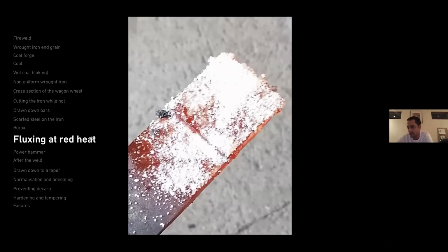It cools down quickly and you have to work fast, but not unnecessarily hastily. It has to come right almost on the first time. I'll usually take sort of 2 to 3 heats just to make sure that the weld is completely set. And the minute I start forging down the sides, if there's any sort of defect or bubble, it quickly shows up, and that's that. So you know when it's welded because you can actually see that there's no movement when forging it further.